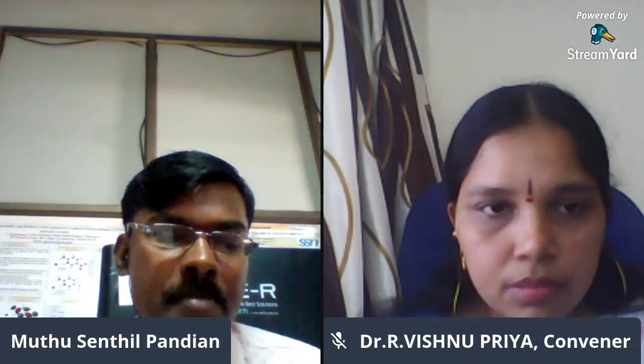So wherever they grow the crystal by the conventional method, due to this temperature instability, several micro cracks appear in the conventional method grown crystal. Because a quartz crystal is a periodic arrangement of atoms. Normally, the crystal will grow like this. But with small disturbances in the conventional method, a lot of micro cracks and milky opaque regions appear in the conventional method grown crystal.